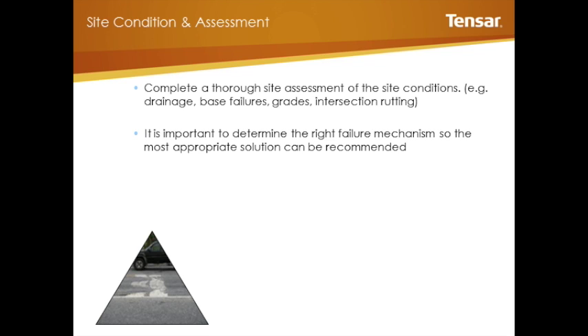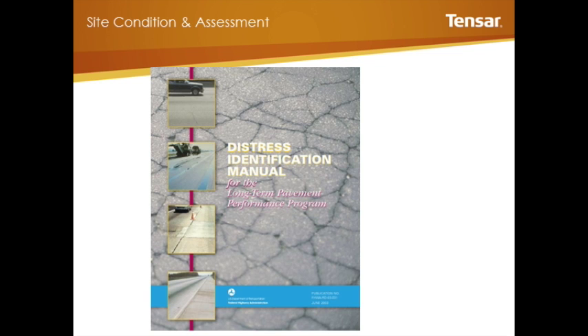For example, this little triangle represents a little bit of lateral shear at an intersection. We have to know if your mixes are walking around, because if they are, you don't need to reinforce them. You have other problems. One needs to sort out the stability of the asphalt first, prior to addressing reflective cracking, because you don't need reflective cracking treatment when the mixes walk around. But it's important to keep this in mind, which is why we typically ask for a profile of the distress types being addressed in your specific area.